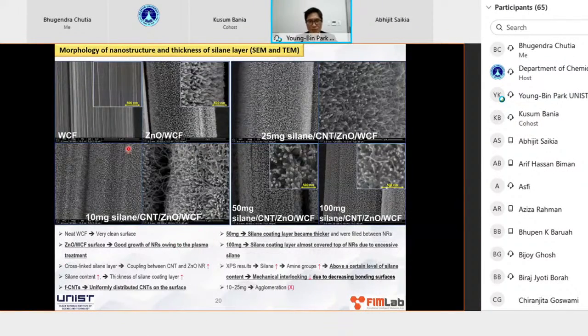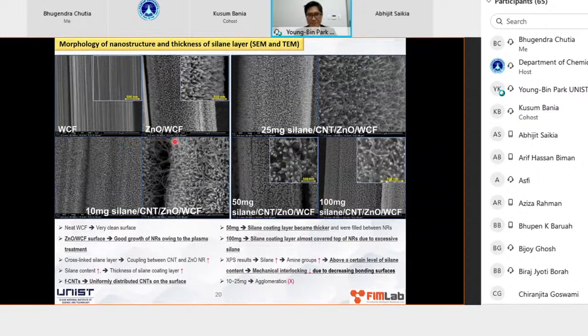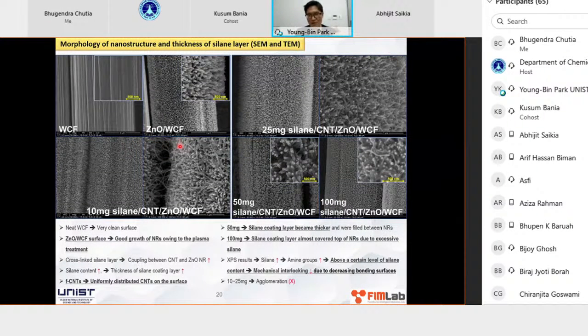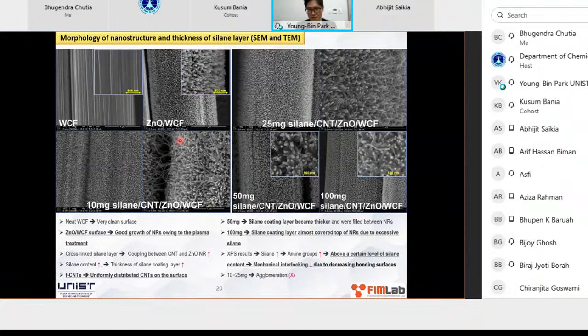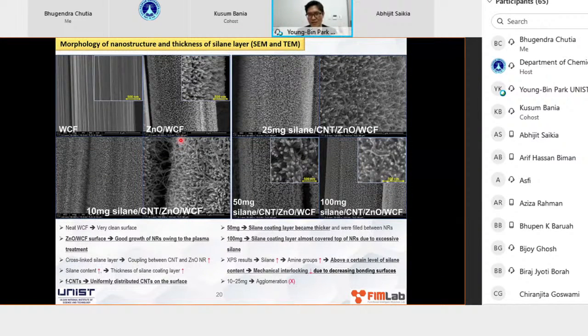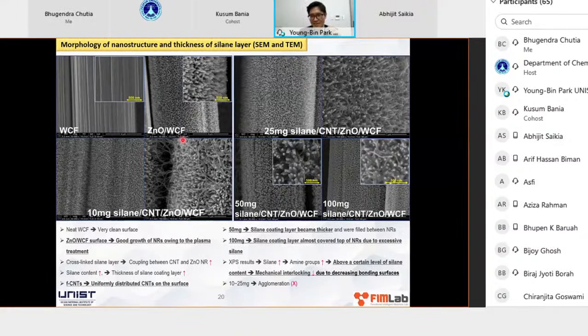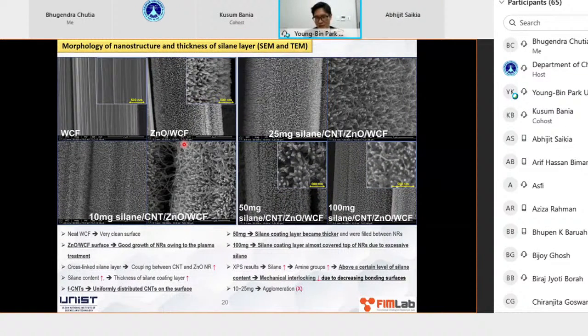And then finally, the morphology of the carbon fiber surface showed that a certain amount, under a certain condition, gave us the best coating condition of the silane. Because remember, silane is a coating on the carbon fiber. Therefore, you do not want that coating thickness to be too large. Otherwise, all the nanorods will be embedded in the sizing, and that's not what we want. We want the nanorods to be exposed on the fiber surface. At the same time, we want the carbon fiber to be uniformly and very thinly coated with the silane.